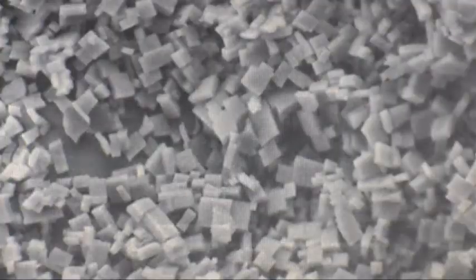This is what the outer surface of the cocoon looks like as we zoom in with a scanning electron microscope. As you can see, there are tiny crystals on it. The first part of our experiment was to find out what the crystals were composed of. So, pure calcium oxalate monohydrate was compared with 2 samples of crystals from the cocoons. We obtained one of the samples by dissolving the crystals in solution and then recovering them. And the other we just scraped off the cocoons.